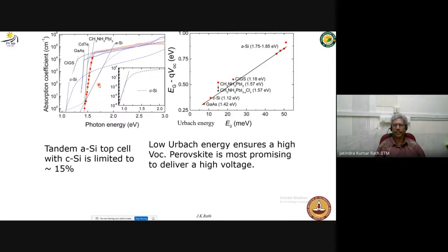There's also one more thing. They told you the tandem cell is a high voltage cell. It's adding of the voltages, so the voltage of the top cell you're adding there is actually a lucrative thing, how good it is. I'm not going to go into what is called the Urbach tail, that is the absorption tail of the material. The absorption tail basically tells how much of the VOC will be. And you can see here that perovskites have a pretty small loss from the band gap to VOC, and that actually makes it attractive as a top cell.